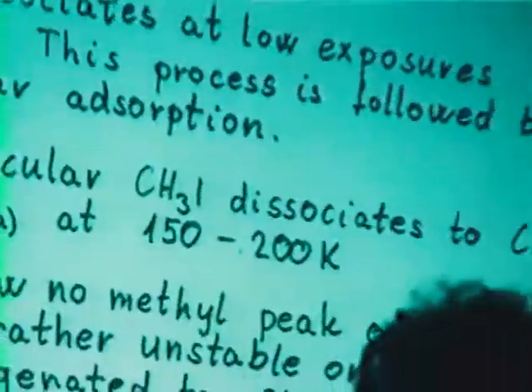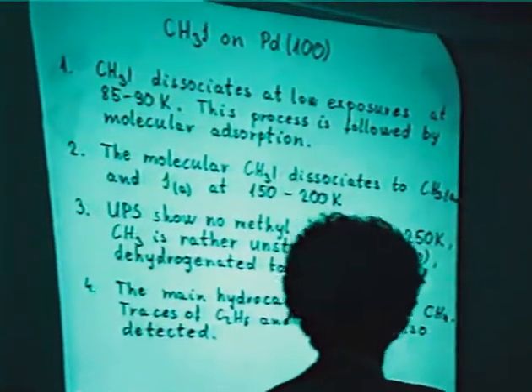We can summarize the statement. This is the dissociation at low temperature and the dissociation of the molecular methyl iodide. In UPS spectra, we found no methyl peak over 250 K. So adsorbed methyl is rather unstable on palladium. It's dehydrogenated to methylene, methylidyne, and surface carbon. The main hydrocarbon form is methane, but we found traces of C2 hydrocarbons.